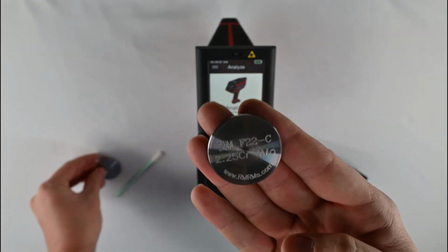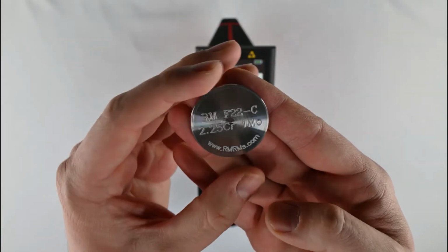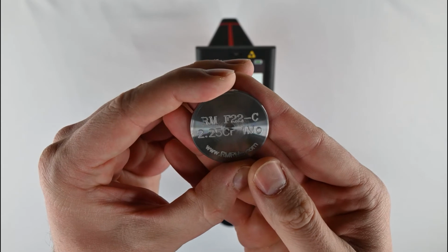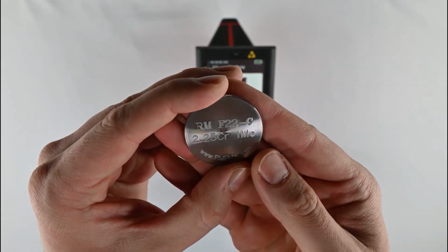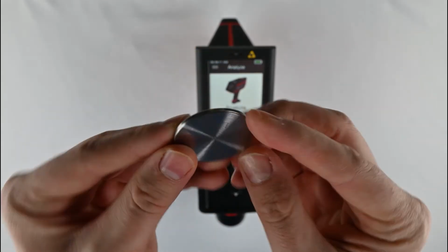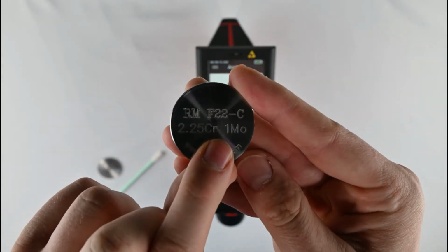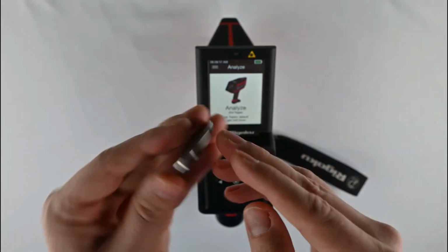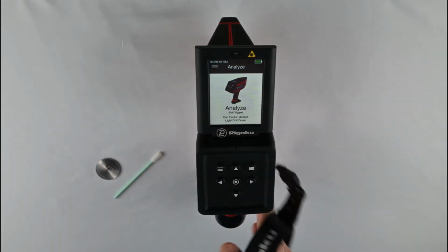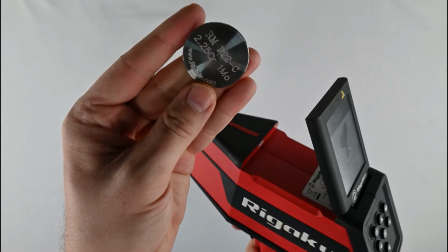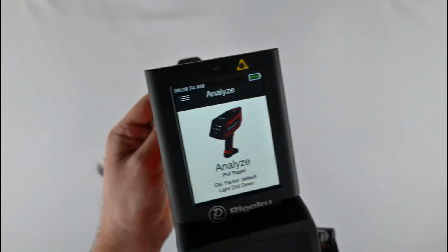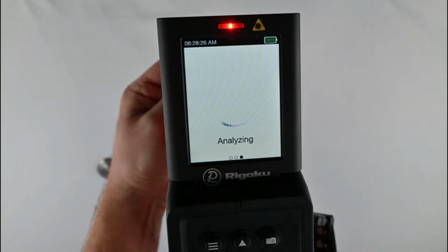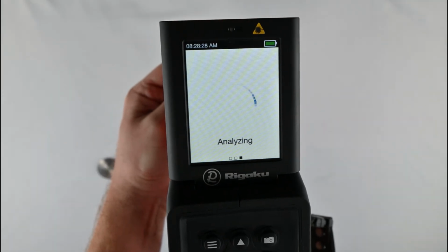Okay, so next up is F22. Now this grade, F22, is the forged grade. It's typically called WC9 if it's cast, and this one is a little bit different. It's 2 1/4 chrome and 1% moly. Now these are both low alloy steels, and this can be used under the same temperature range as F11. It also is slightly stronger at 75 KSI for its tensile strength.